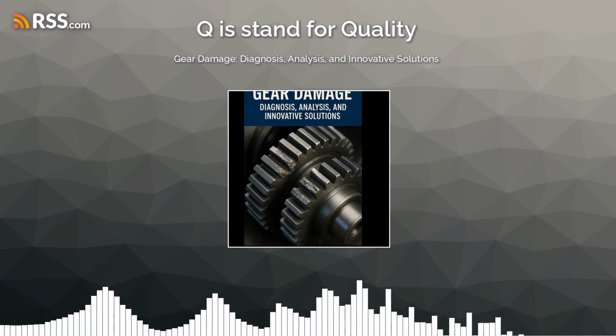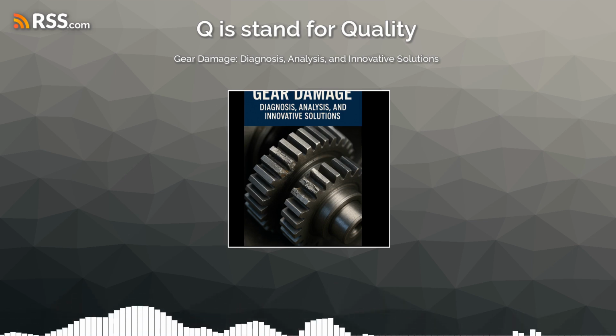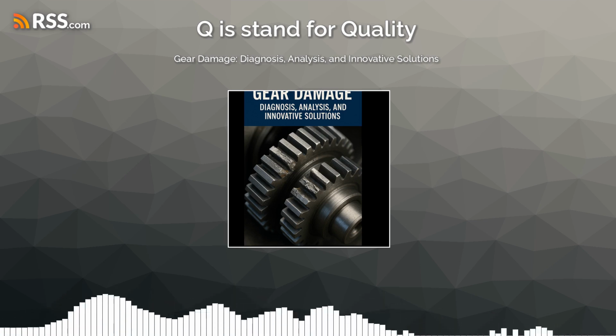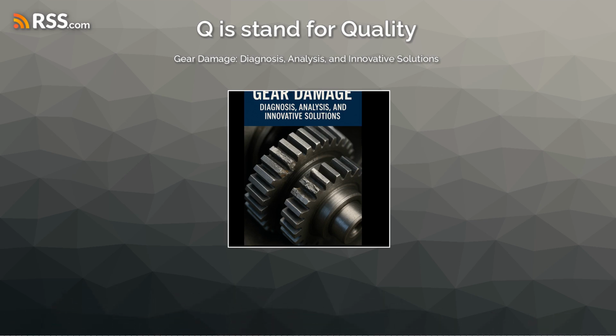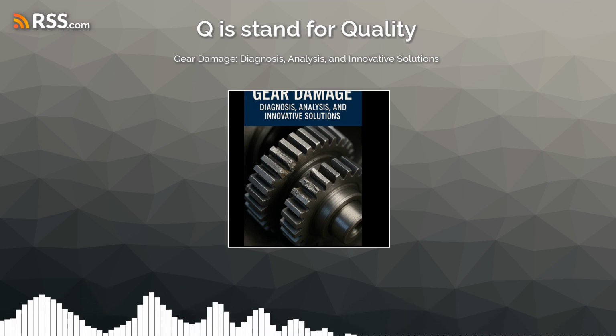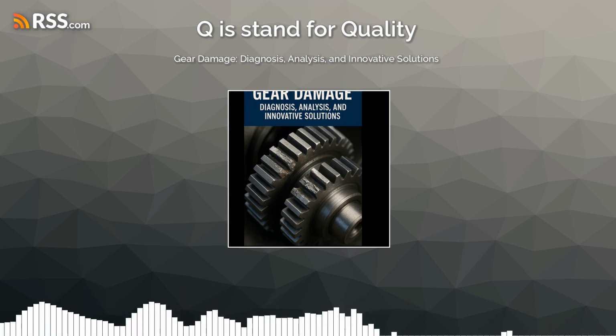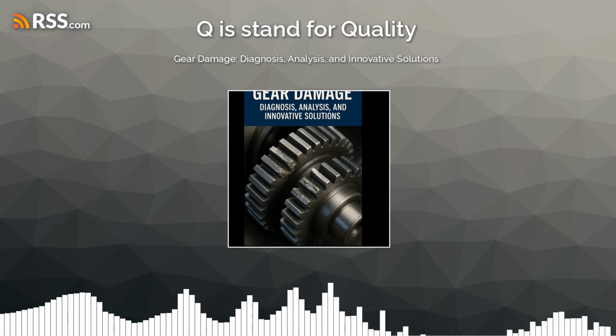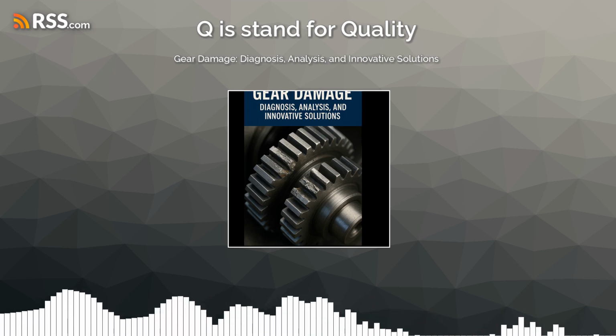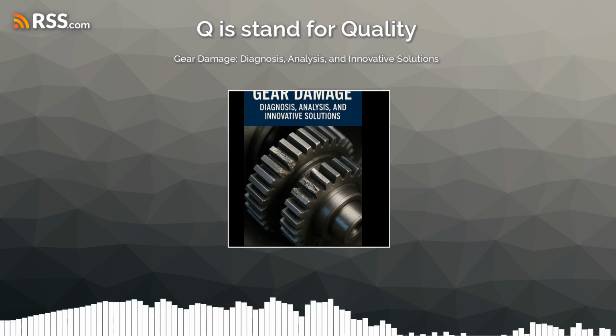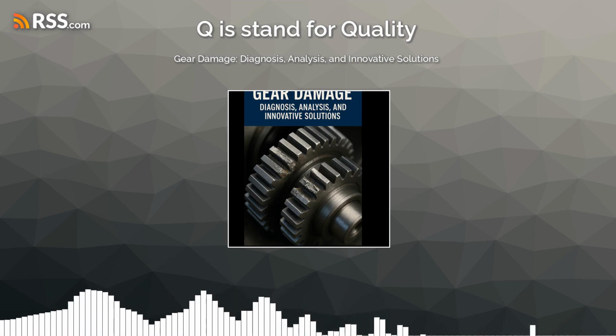SEM takes it to a whole other level. It lets us see the microscopic landscape of the fracture surface in incredible detail. We're hunting for features invisible to the naked eye. Tiny non-metallic inclusions within the material, the intricate texture of the fracture edges, subtle discolorations hinting at corrosion, characteristic arcs or patterns, and crucially, those telltale fatigue bands or striations.